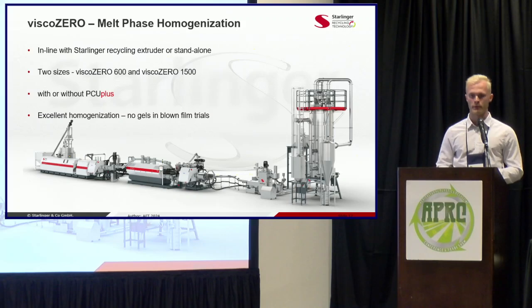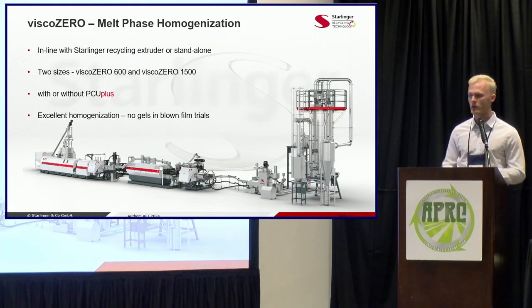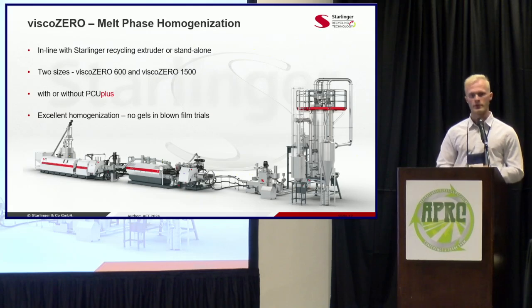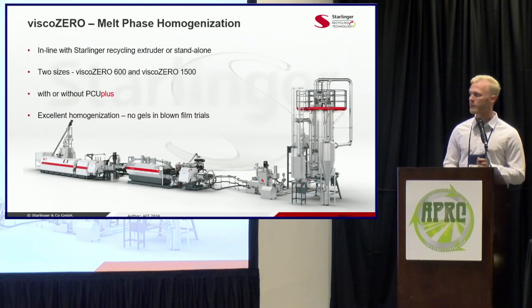And the interesting part of this machine is the result on low density or linear low after a blown film trial. So we've done a lot of work with European ag film recyclers, and the results are astounding. There are no gels, no inclusions in this melt after running it through this full system of the Starlinger recycling extruder and then the Visco Zero. So the quality is really superb, and we think that this is the future in terms of processing a really great PCR regranulate from PCR film.